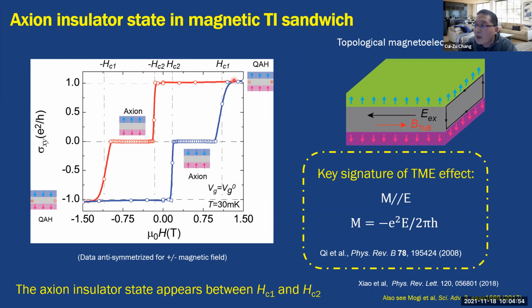We can say that at very high magnetic field, this is the quantum anomalous Hall state. When you sweep back the magnetic field, the chromium doped layer, because its coercivity is smaller, will flip first and form this anti-parallel alignment. The Hall conductance becomes 0. And if you sweep further, the vanadium doped layer will also point down. This is quantum anomalous Hall again. And when you sweep back, it repeats this behavior. This is just the axion insulator state, the zero Hall conductance plateau in the Hall conductance curve.